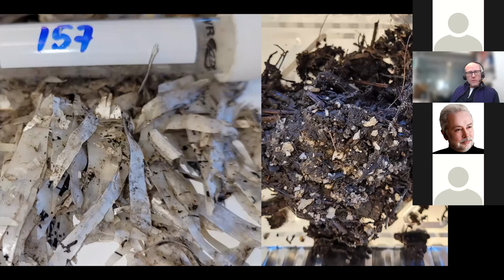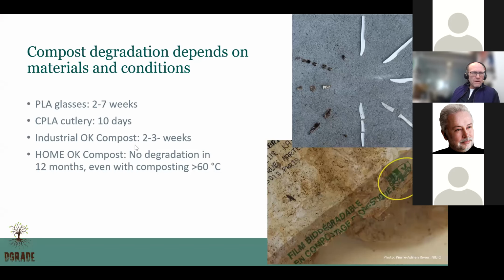This is a little bit how it looked inside the pouches when they were dug up after only a week or two here. And eventually after 5 to 7 weeks, the plastics, the PLA, looked like these very small parts that could be the only thing we could extract from that.